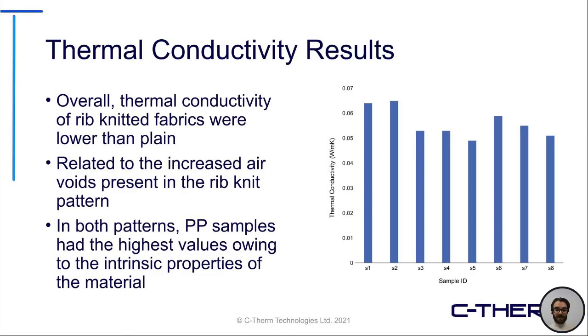However, in both patterns, regardless of the structure that was being used, they did notice that the polypropylene-based samples did have the highest overall values. Because, like I said, there's a lot of things that influence your measurement: the base material that is being used, as well as the different knit structures. But across both knit structures, they found that there is a singular material type that did have the highest performance metric that they were looking for.